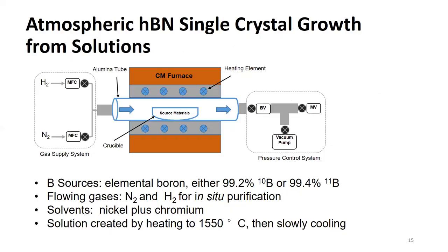So the process we use is actually quite simple. We have a single zone temperature furnace with source materials here, heated up to 1550. This is all at atmospheric pressure. We feed hydrogen and nitrogen, mostly nitrogen, over our source materials. For source materials, we can either use pure hexagonal boron nitride, so already compounded, or we can use separate sources.